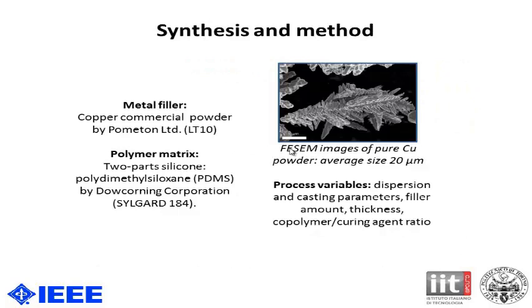As you can see, the particles are quite spiky, and they have an average size of 20 microns. We used as a matrix a polymeric matrix of 2-part silicone. By controlling processing variables like dispersion and curing parameters, filler amount, and so on, we are able to finely tune the sensitivity of the material.